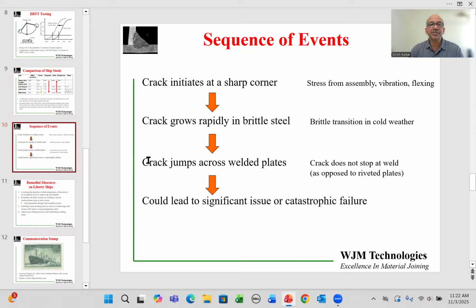Because it was a welded structure, the cracks also jumped across welded plates. That is one of the downsides of welding: if the crack starts growing and you cannot stop it, it will jump across plates and go all the way to the end. And this would not have happened on a riveted structure. Depending on location and direction of the crack, there were situations where it was a catastrophic failure and the ships would literally break into half and sink within minutes.